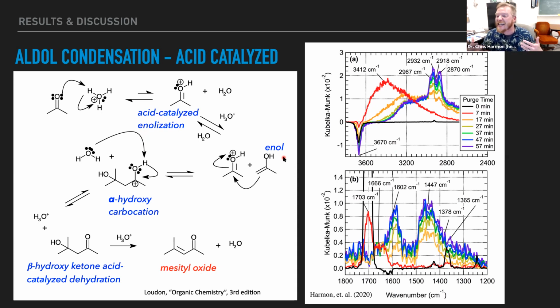So we see chemistry. So here is the classic aldol condensation mechanism. And I'll just point out a few features of this mechanism. So we can see in the first steps, the production of water, right? Stable leaving group water. And you notice here in my spectrum early on, look at this, we got this big whopper of a hydroxide asymmetric and symmetric stretching, right? And that's different than that dangling hydroxide spectrum. So it seems reasonable that this could be the production of water.